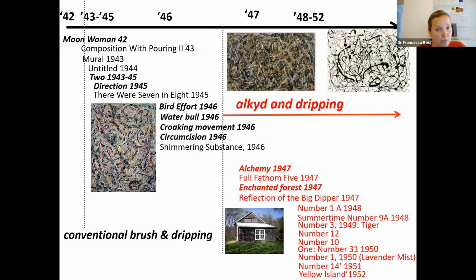As I told you before, we had the opportunity of investigating 11 paintings by Jackson Pollock at the Peggy Guggenheim Collection. We then integrated our study with the previously published data regarding the identification, also through the extractive method, of the painting media on different paintings. And here we confirmed through the non-invasive study that alkyd is strongly correlated to the dripping technique. And we confirmed 1947 and the years after as years in which Pollock used the alkyd medium. But we could also anticipate the use of this medium by one year, to 1946, also using, and not experimenting yet with the dripping, but using a more conventional technique.